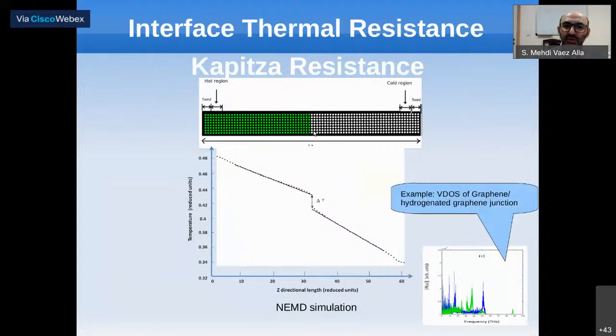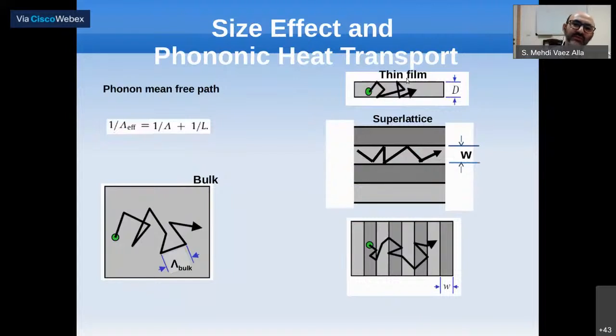If we have a boundary in a given system, boundary means that if we have a complete lattice at left and the same at right, but a different material, for instance, by changing the atomic mass of material at the two sides, the vibrational density of states of phonons at the two sides of the system becomes different, and heat carriers from the left to the right will be scattered at the interface. This feature is called Kapitza resistance of interface, and it is a very important issue in decreasing the size of the system and going toward low-dimensional systems.